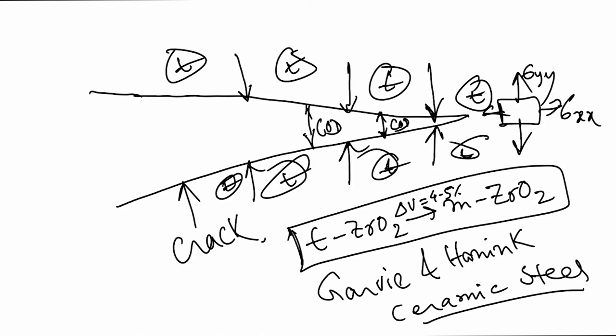So from this very basic information, on how tetragonal zirconia can influence the crack growth resistance in the microstructure, it should be clear to the students that this tetragonal to monoclinic zirconia transformation can be invoked at the crack tip, and that will lead to crack tip closure or crack tip blunting, that will lead to an increase in the crack growth resistance, ultimately K1C, that mode 1 critical crack tip fracture toughness, also would increase. So if the driving force for the crack propagation is reduced, that leads to the increase in the fracture toughness. A couple of things that let me also tell you in another slide.